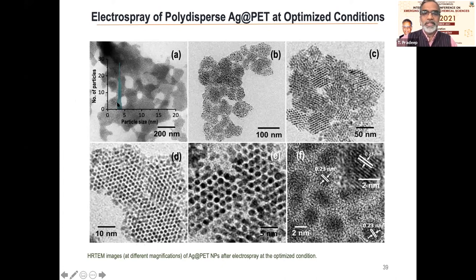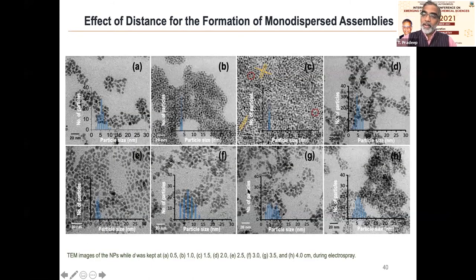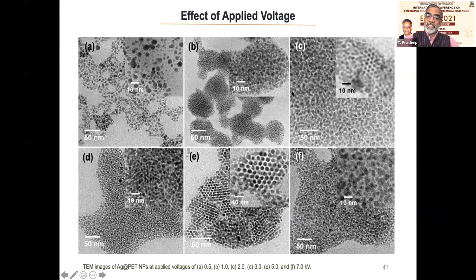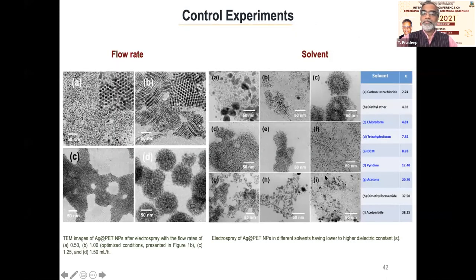Now, when a droplet is falling on the surface, you can vary a number of parameters. For example, you can vary the distance from the tip to the surface. And you see that at an optimal distance, you get such organized particles. You also vary potential. At a given specific potential, you see that such things happen. Other potentials, they don't do this. You can vary things like flow rate and solvent and say that this happens in certain conditions. And then, with a number of studies, you build a mechanism.